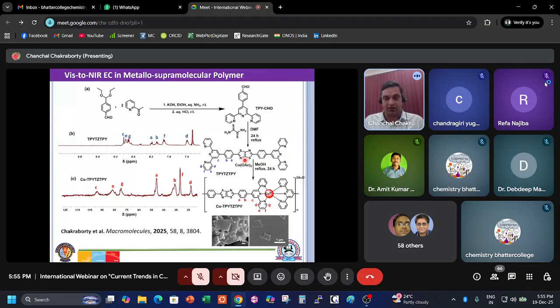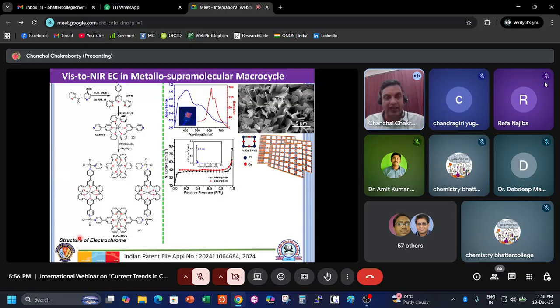Along with that, we can introduce some porosity into the polymeric structure. The earlier polymeric structure was a one-dimensional polymer, which did not have any intrinsic pores. But if we provide this kind of square complex, then we can generate some pores, and pores are required for swift ion diffusion. We prepared this and characterized it well by NMR and other spectroscopic techniques, mass spectroscopy, and also photophysical studies like UV-visible and emission studies.